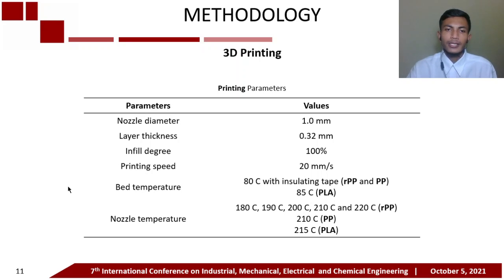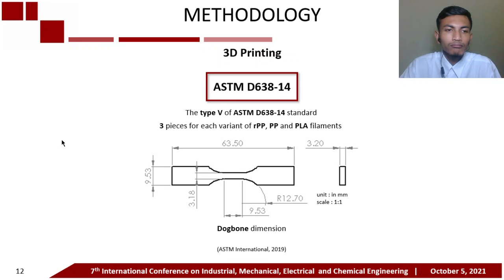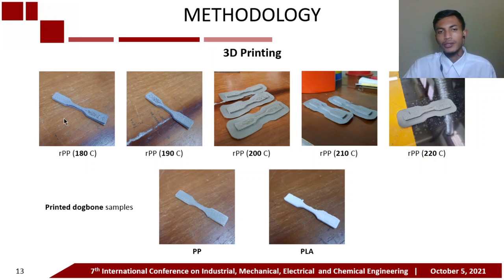The 3D printing process is carried out to build the dog bone samples for tensile testing. Samples were prepared with nozzle temperature variations at 180, 190, 200, 210, and 220 Celsius, as well as several parameter settings that I list in the display. Besides that, dog bone samples from industrial standard PP and PLA filaments were also prepared as benchmarks. The dimensions of the dog bone samples were made according to the Type 5 ASTM D638 standard, and three pieces were prepared for each variant.